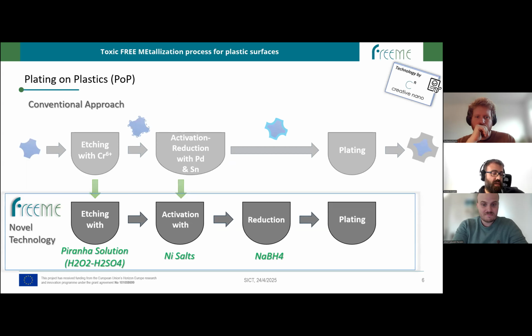So in this concept, in this scope, here comes FreeMe, where actually in the etching process, the hexavalent chromium has been proposed to be replaced by Piranha solution, which is a mixture of hydrogen peroxide with sulfuric acid, while the activation and reduction stage can be separated into two consecutive stages, where the first activation happens with the use of nickel salts, while then the nickel ions, which have been chemically adsorbed on the etched surface, are reduced by using sodium borohydride. And finally, we have, of course, the plating stage, which more or less remains the same as the conventional approach.